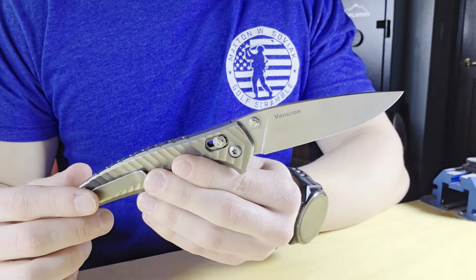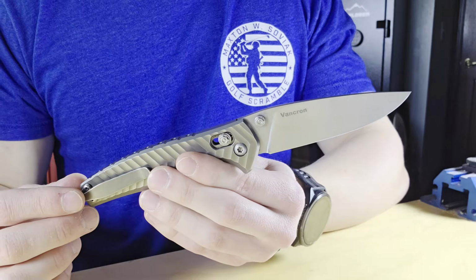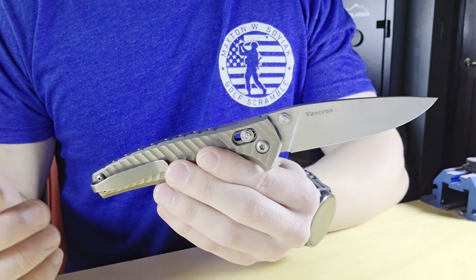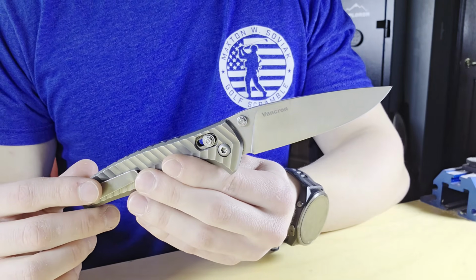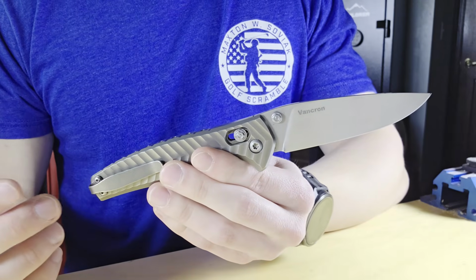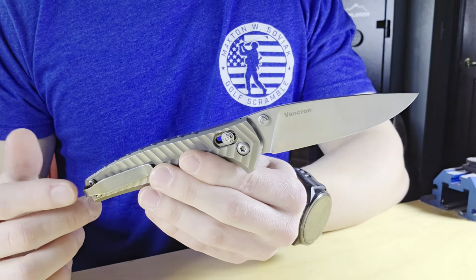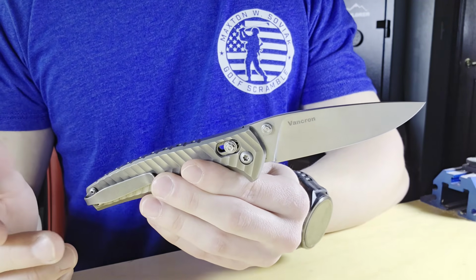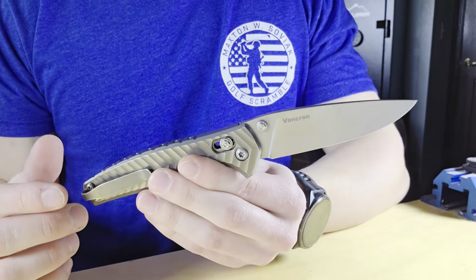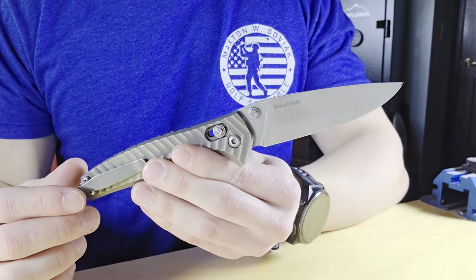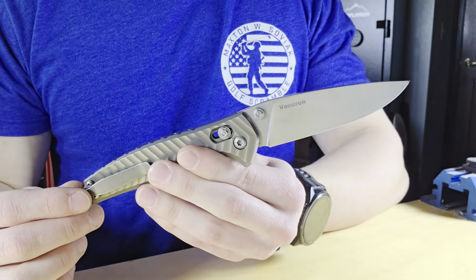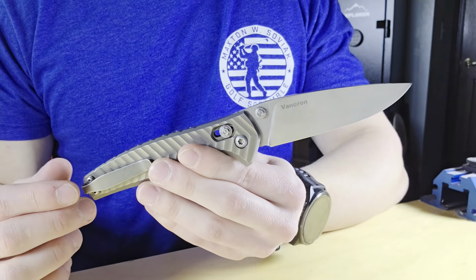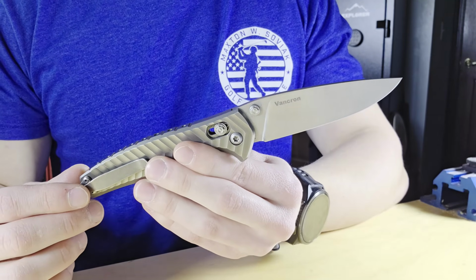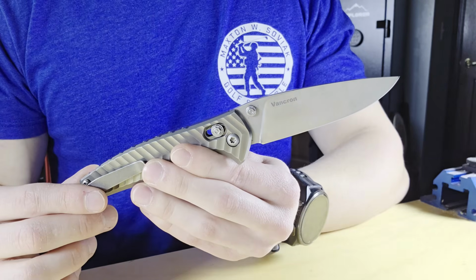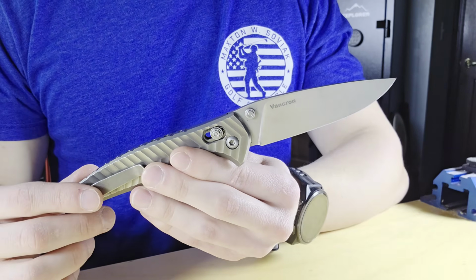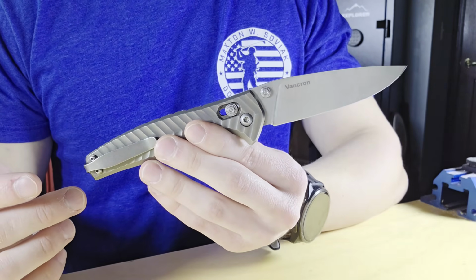a 1-inch section. That is a staggering amount of cardboard, and I honestly felt like I made a mistake somehow in the testing. I followed the exact same protocol that I always do, the same sharpening, the same cardboard, everything. And the result was so surprising that I ran another test with a different steel that I'd already tested to make sure that there wasn't something odd going on with this batch of cardboard, and those results came out within spec. So no issues with the cardboard. This thing's just an absolute freak.